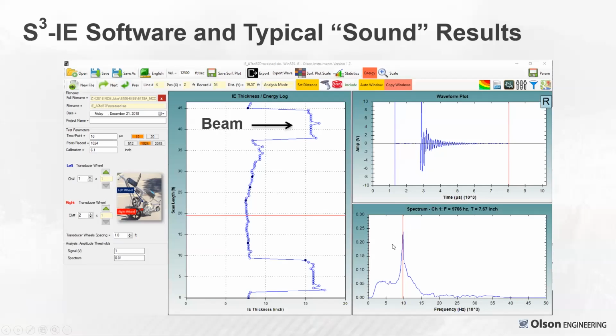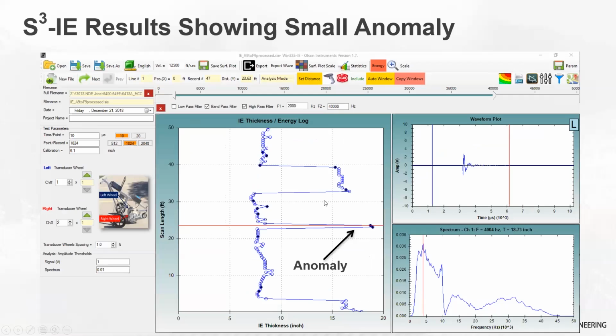Over here, you have the time domain and of course the spectral plot showing a nominal thickness at this cursor location of just under 8 inches. So this is a sound location. There's nothing particularly worrisome going on here. What's interesting, I think, is that the same scan can show the beam and the slab thicknesses quite readily. This is a result showing a similar slab and beam result, but right in the middle of the slab in an area that should be nominally 8 inches, we had several points that were very, very thick. That would indicate in this case, either a shallow surface delamination or a large void or some other honeycomb or some other issue in the result.